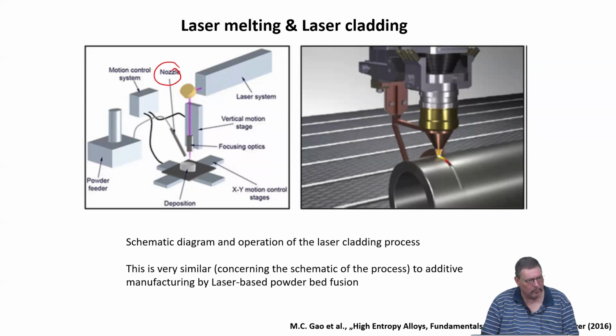Obviously, we have all the pros and cons as for arc melting here, because also rapid solidification, directed heat flow during cooling, microstructures that form are probably far from equilibrium. So again, one needs to do some post-processing treatment if you are not interested in this metastable microstructure. If you want to have a stable microstructure, you have to do some annealing, maybe even rolling and annealing in order to form a good equilibrium structure.